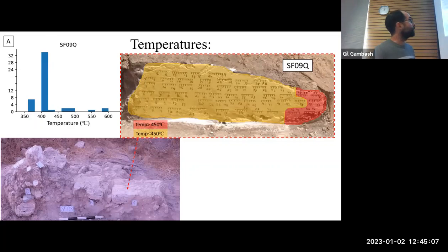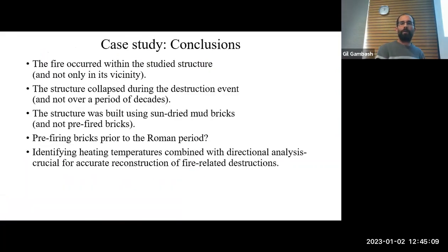destruction of this structure. So we got to these conclusions from this case study: that the fire occurred within the studied structure. The previous paper suggested that there was fire in the vicinity, but not in the structure itself. I think that we showed, because there's no other way to explain the in-situ bricks that were fired and recorded the magnetic field.